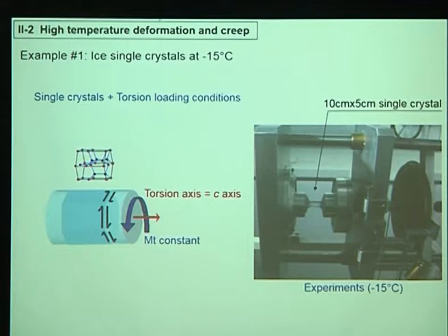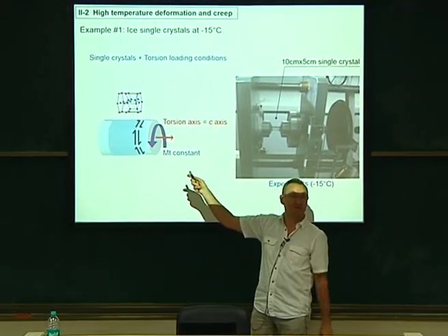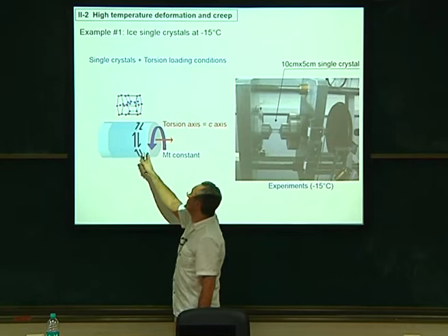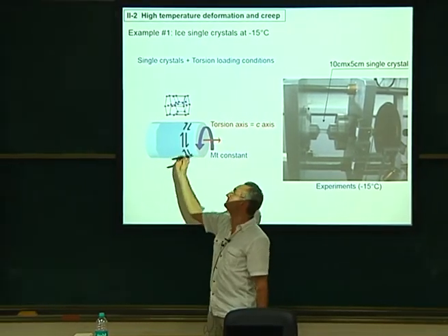Ice is like this. So this is a real ice, single crystal. So single crystal that we were able to grow in the fridge. So you go in your fridge, you need to cover, of course, because it's very cold. It's minus 20. At minus 20, you make your single crystal grow. You machine your single crystal. You are able to identify the C-axis, which is an hexagonal structure. So you do your best to have your C-axis toward the axis of your cylinder that you machined, like this.